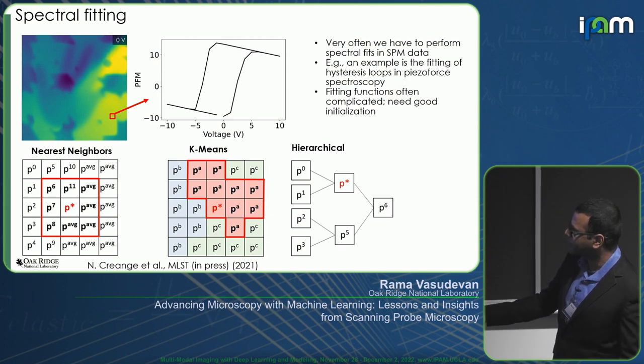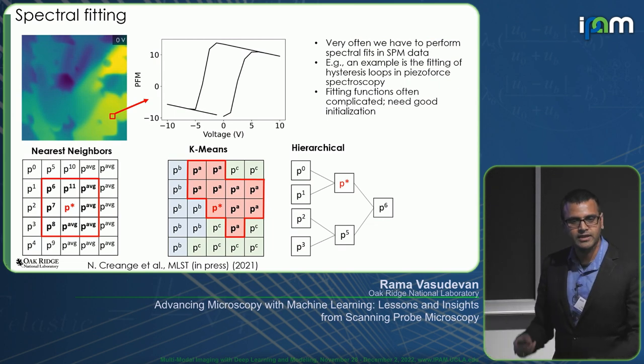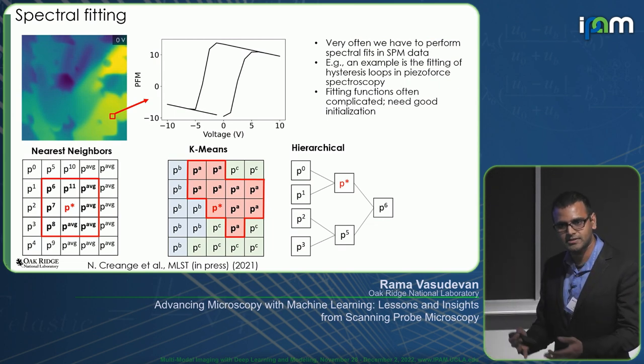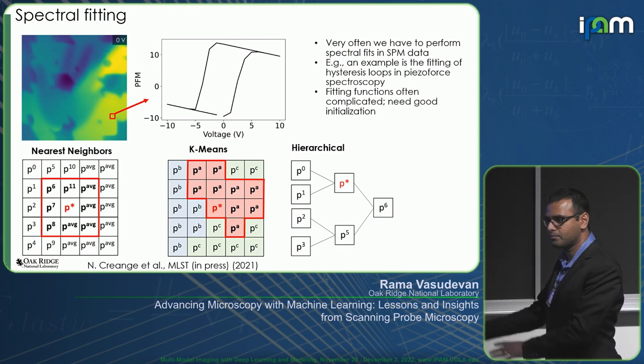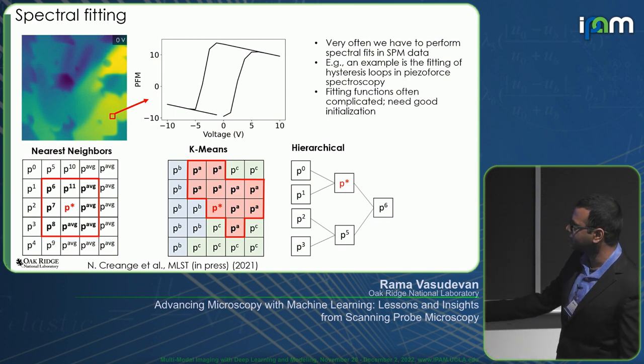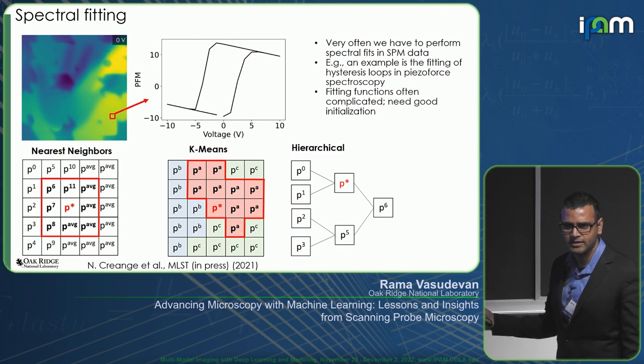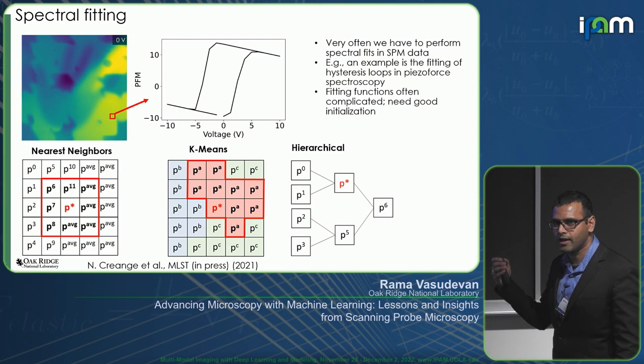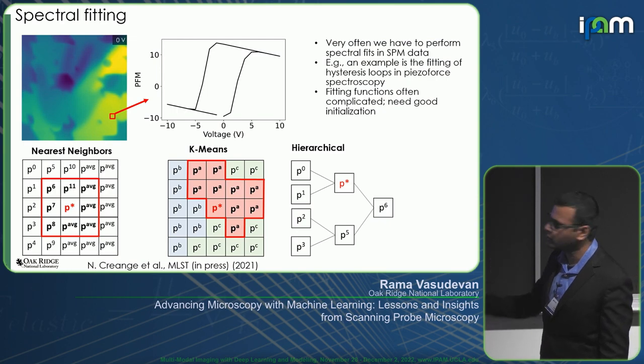So this is called the nearest neighbors approach. We can also use a k-means approach where we cluster the data, fit to the cluster centroids, and then propagate the results of that fit to the cluster members. And there's also a hierarchical approach which we can use. But basically, we are leveraging the fact that we have so many different spectra collected across the grid of points to improve the priors that are used for functional fits.